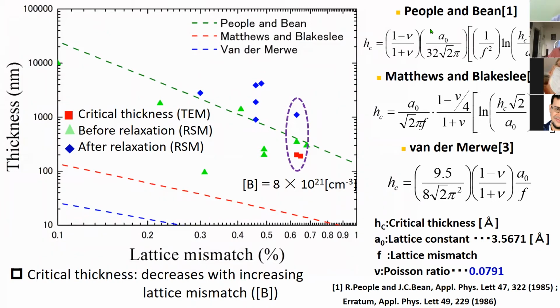So we borrowed these ideas, and also the theory of thickness and lattice mismatch. We plotted many samples, and the error bars are large, but anyway we are nearly these lines where people, I mean the group, suggested in the 1980s or 1990s in the silicon and silicon germanium case. Because silicon germanium and diamond have the same crystal structure, I think this kind of model can explain our critical thickness.